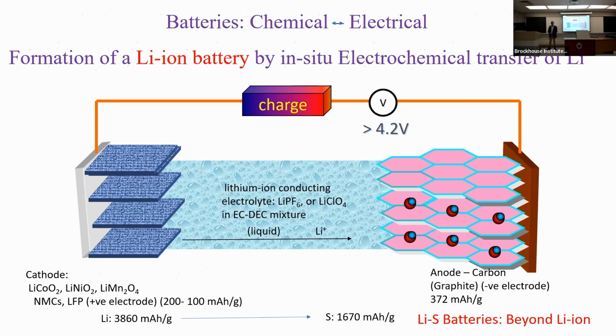If you look, it's a capacity in terms of charge. It has 372 milliamp hour per gram. And if you look at the cathode, the value is somewhere between 100 to 200 milliamp hour per gram.